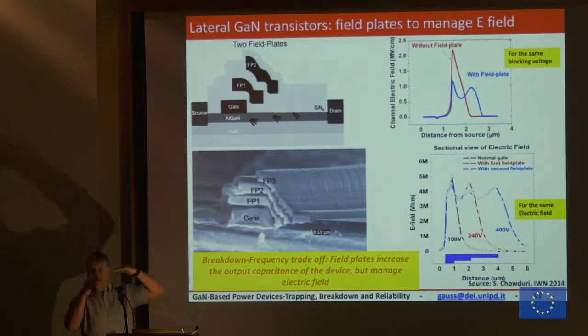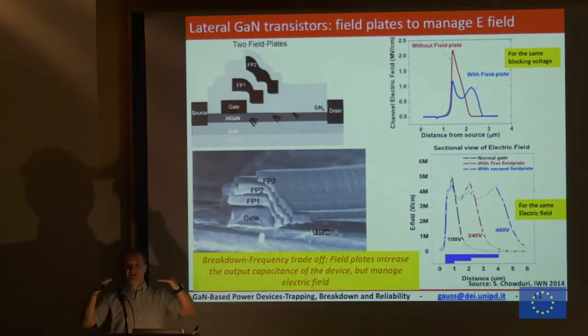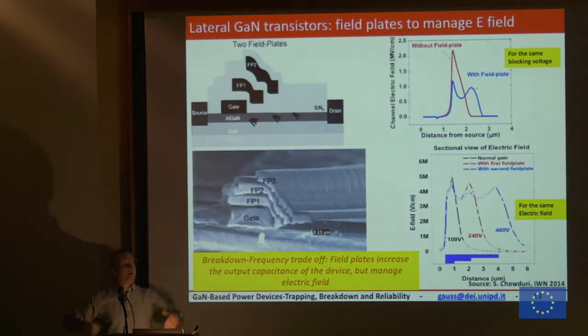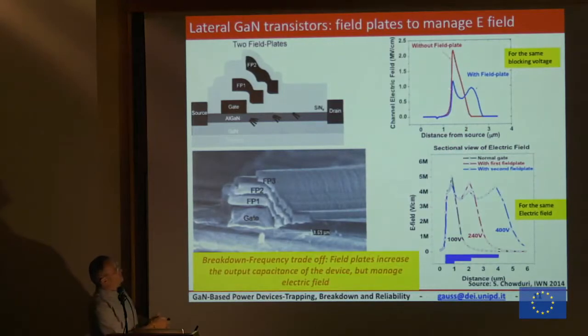Just because you make this field plate, you lower the maximum electric field, you make your field wider, and then you can go much higher voltages, because whenever you increase the VD, then you raise up all the blue curve in this case. And if you do 3 or 4 field plates, you may end up with a much better situation, and you can go very high voltages, okay?